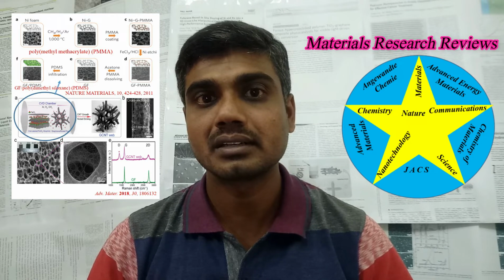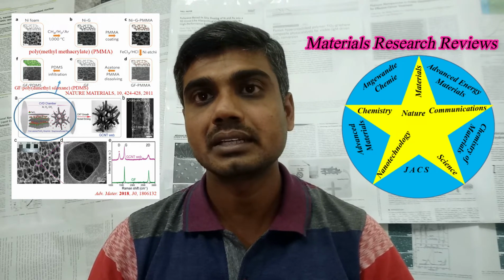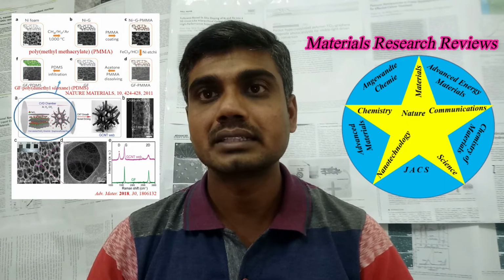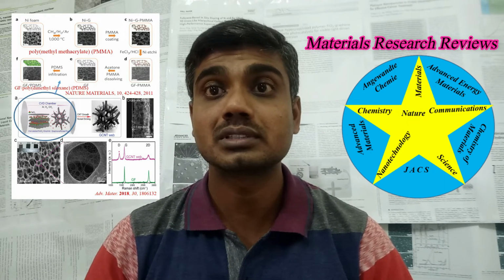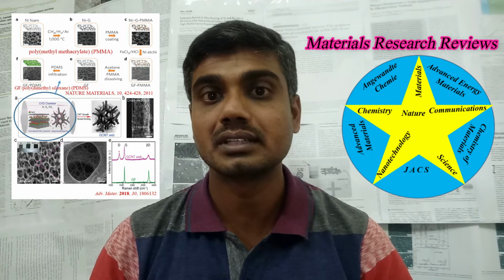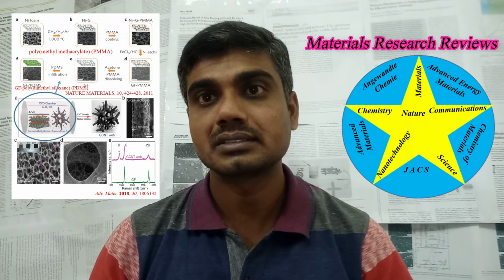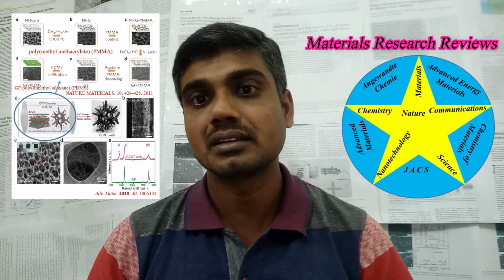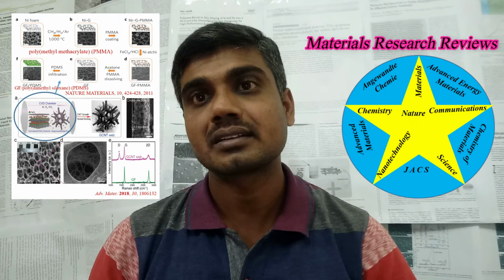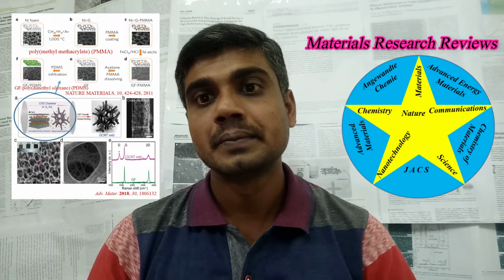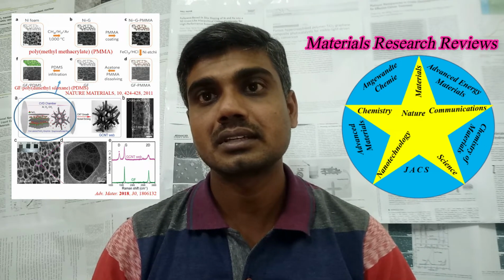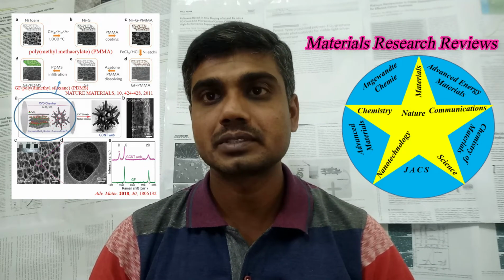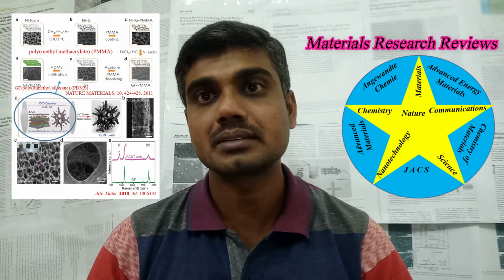After that, the nickel foam in methane, hydrogen and argon atmosphere, at high temperature, more than 1000 degrees, they used the CVD method to synthesize the graphene nickel foam. After that, the nickel is etched using iron chloride and HCl. Once the nickel is etched, graphene foam is formed. This is the first step they did.